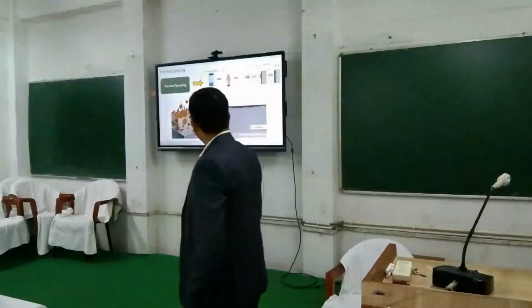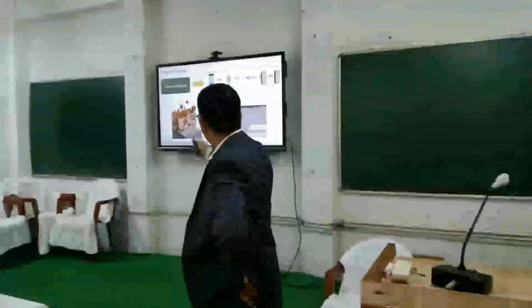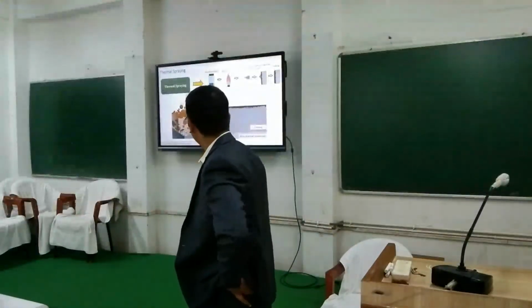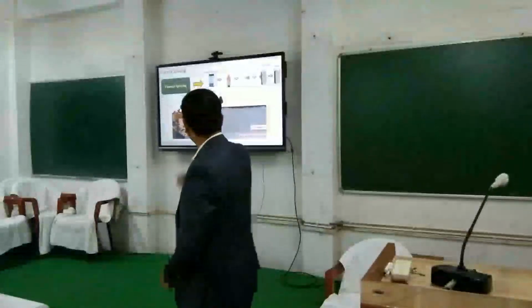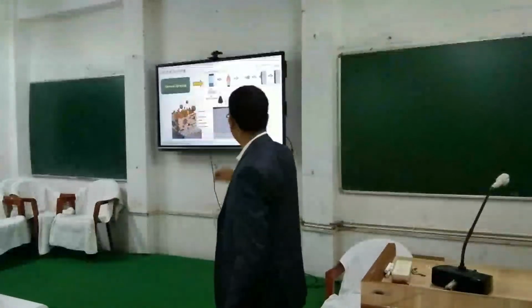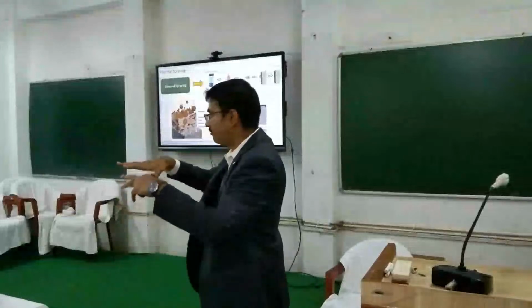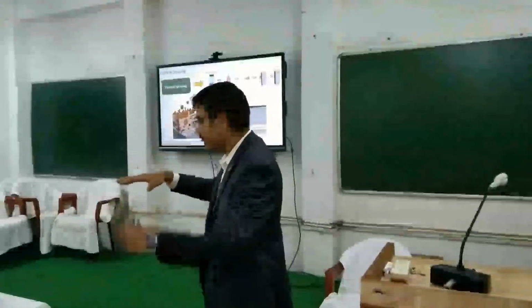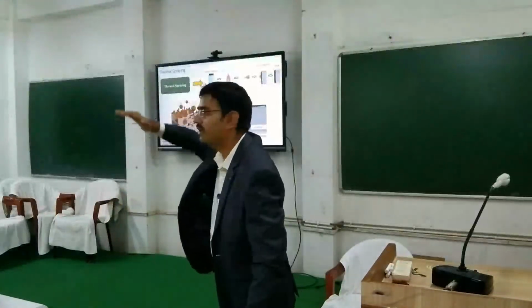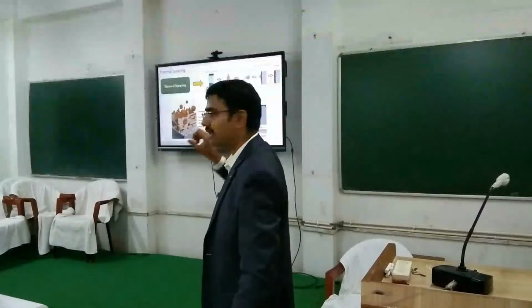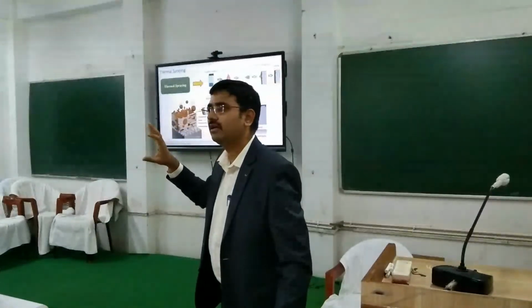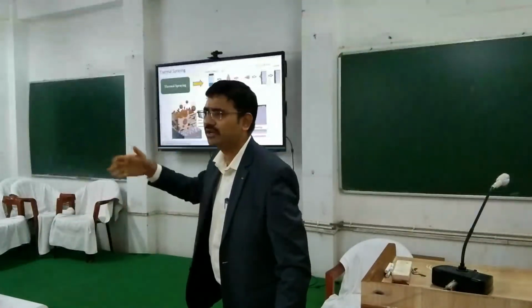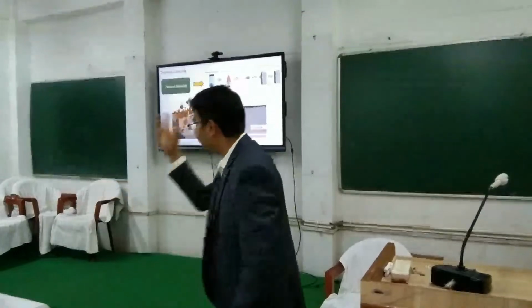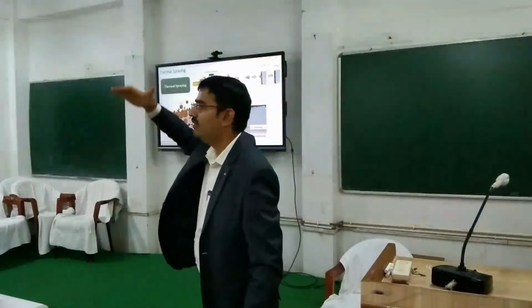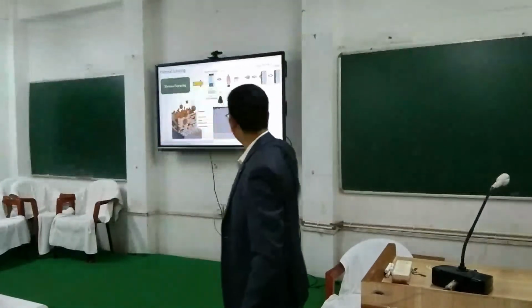Okay, so we see that the powder particles are coming in the figure on the left hand side bottom, where you have powder particles coming up and they are deforming, or melted particles are solidifying, and then you actually start building up a coating. Here the powder particle sizes we are looking at are typically tens of microns, that is 40 microns, 50 microns. So you start at a powder particle level and then you slowly build up the particles. So this is how a coating looks.